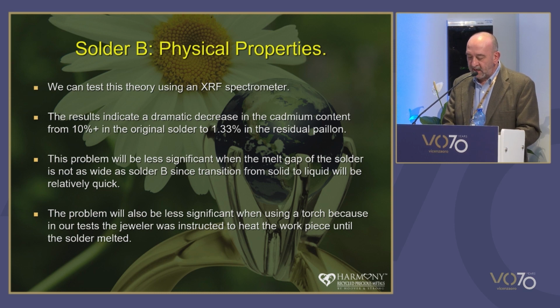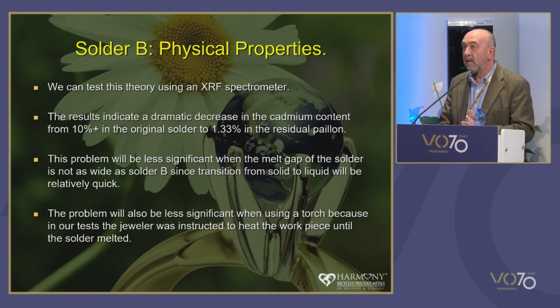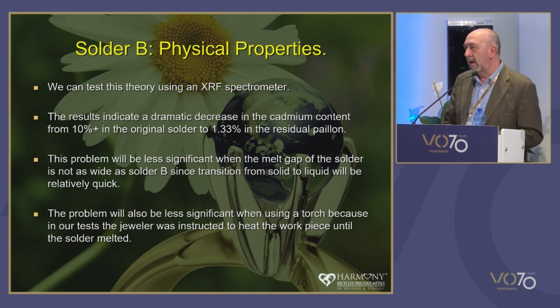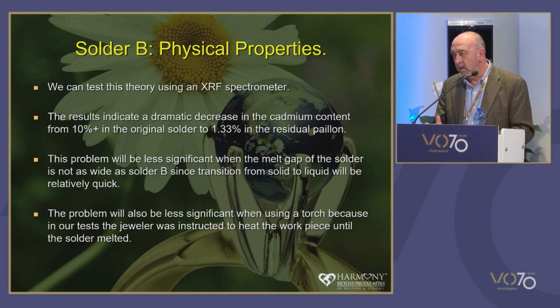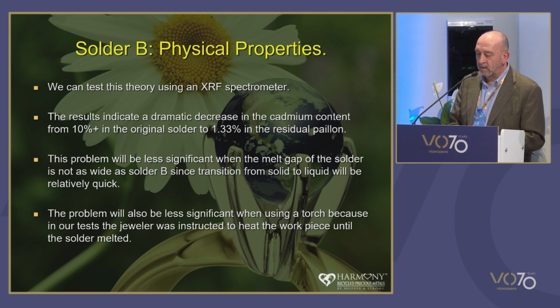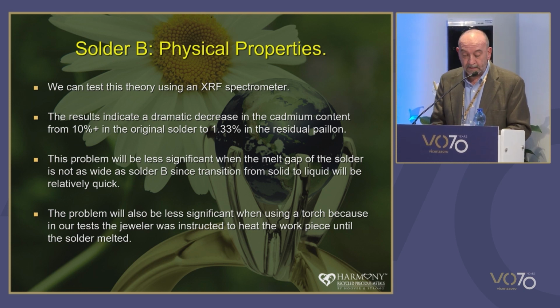It's going to be less significant when using a solder with a narrower melt gap because you're going to achieve liquation very much quicker. And the problem is going to be less significant when the bench jeweler is using it for torch soldering, because in our case in particular, we instructed the jeweler to heat the workpiece until all the solder had melted. So all the solder's going to melt.